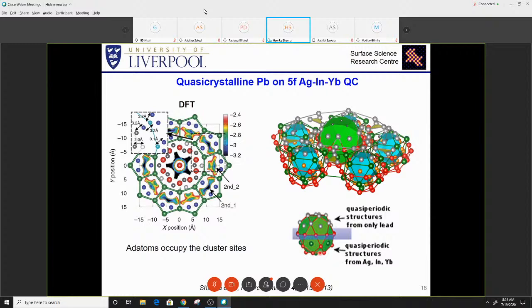The interesting thing here is if you see the distance between the lead atoms at various heights, they are comparable to the lead distance in FCC. So this distance is strong enough to stabilize such a complex structure with quasicrystal order.